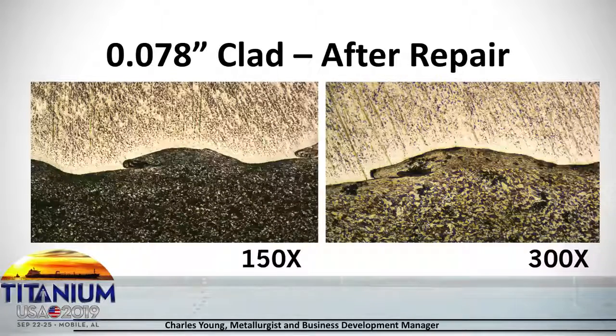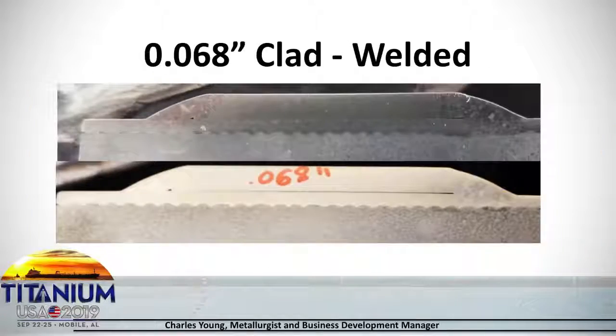Going down to 0.068, again, you see the weld area over on both sides. You see a little bit of disruption here, but if you look at it under the microscope, you don't see anything. So that's just, I would say it's nothing there. So at 0.068, you still have a very good repair, and you don't have to worry about messing up the titanium to steel interface.